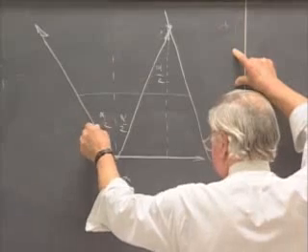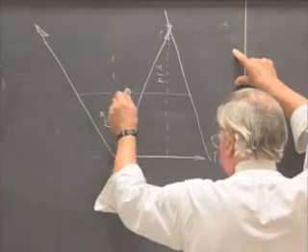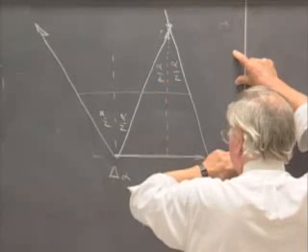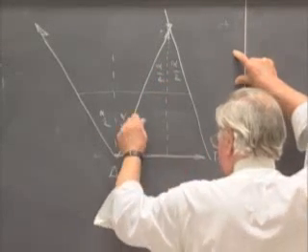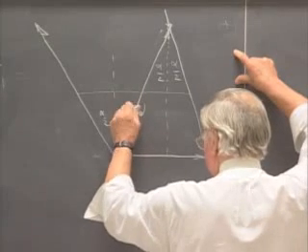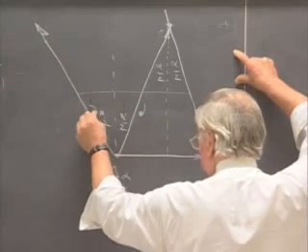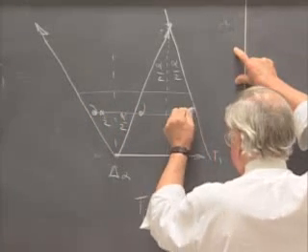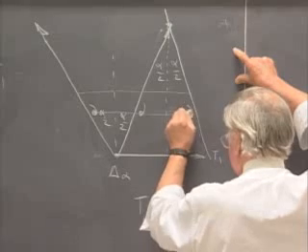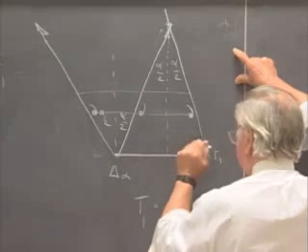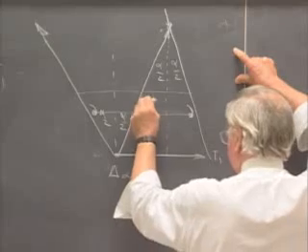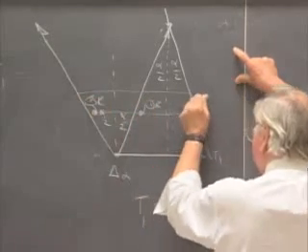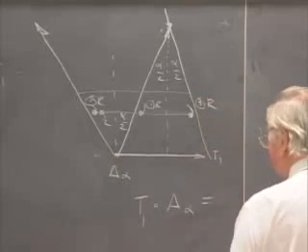And this line is inclined to the perpendicular by alpha over 2, so this angle in here is also alpha over 2. So the answer is that if I rotate from one location to another by a rotation alpha, and then pick up that motif or the entire space and translate it by the original translation T1 to get a third one, this is number 1, right-handed, say. Number 2, right-handed. This is number 3, it stays right-handed. Has to be related by a rotation.